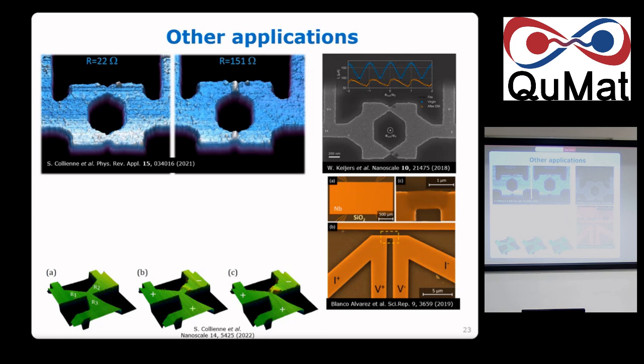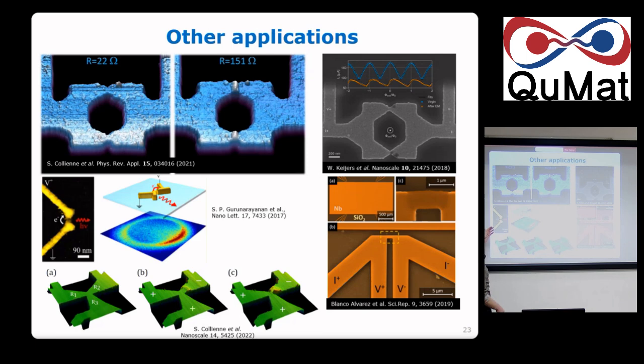But you can also make a heater. For example, in this sample, we wanted to have a superconductor and next to it a heater of another material. Difficult to do because you have to do overlay alignment of the position. No, we just take the niobium and electromigrate it. You don't see very clearly, but you change the properties and it becomes a normal metal. So it's a handy way. Some colleagues have even used it for making antennas, where every time an electron jumps they have a directional variation.